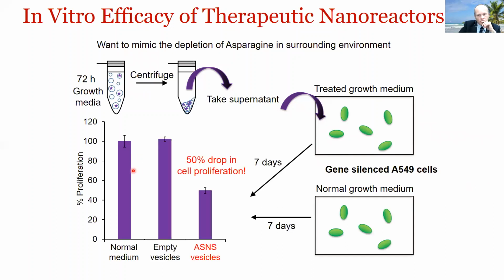And after 7 days, we can see that with just the normal media and the control with empty vesicles, we see no change in proliferation. But we were able to get about a 50% drop in proliferation when we were using our ASNS vesicles. And this really does highlight that the encapsulation of this therapeutic enzyme within these polymersomes still allows for increased activity. We propose it would also allow for increased circulation times due to the larger size, and this coating effect, which is within the polymersome, is much more effective than just PEGylation, because it really does protect the delicate and active enzyme, or therapeutic, from other things such as the antibodies and proteases.